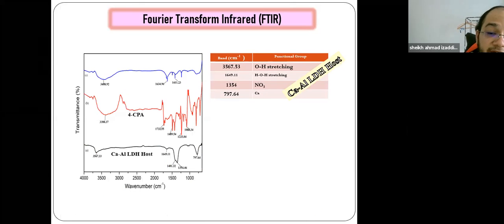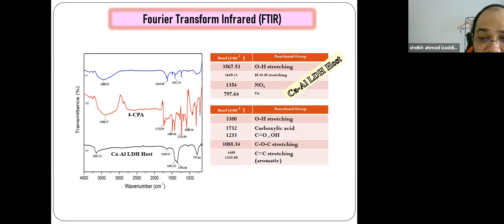Now for the FTIR, the FTIR spectra show 3 different infrared bands which were prepared using calcium nitrate and also aluminum nitrate nonahydrate. The most important aspect to highlight is the presence of the nitrate group band, which is in the range of 1350 to 1400 wavenumber. So this peak should disappear or decrease in intensity to confirm the successful integration between calcium aluminum and also 4-CPA.